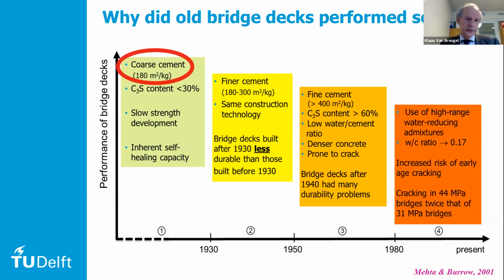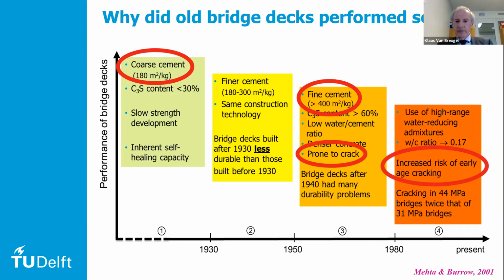If we look at the first period, we saw that they used very coarse cement and not much cement per cubic meter. Later on, they used finer cement, and it turned out to become prone to cracking. And in the last period, there was an increased risk of early age cracking because of high cement use, fine cement, but also a very low water cement ratio. If we then look back to this first period, we saw in those old bridge decks that performed so well that they had a very good self-healing capacity. And that's one of the secrets, I think, of cement-based materials.